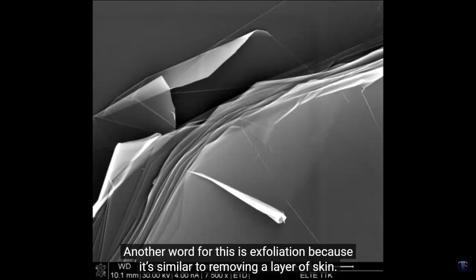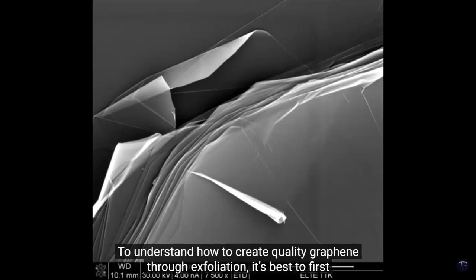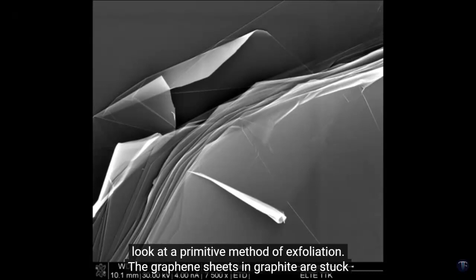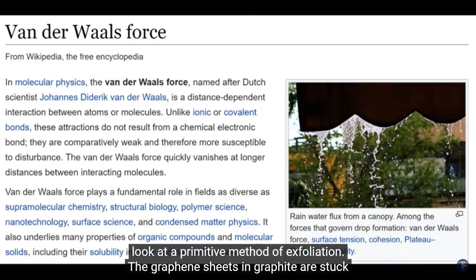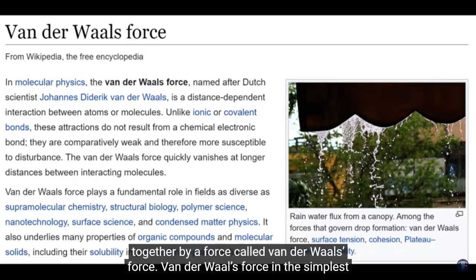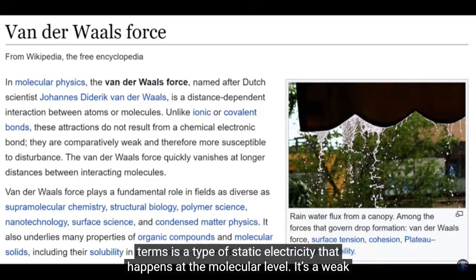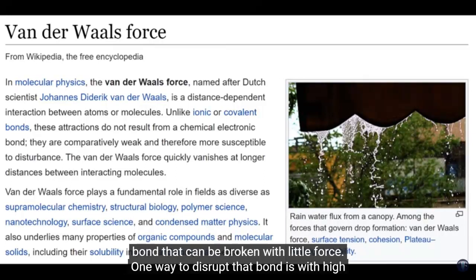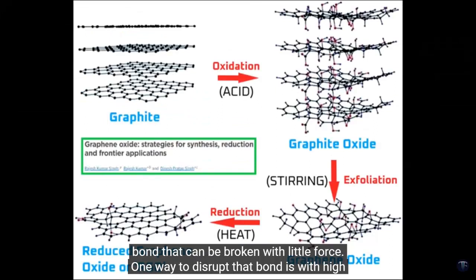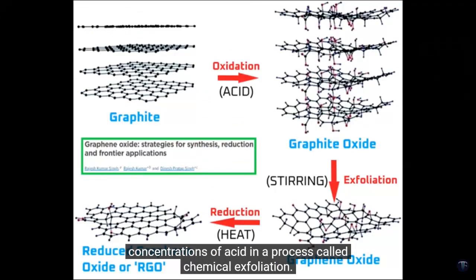To understand how to create quality graphene through exfoliation, it's best to first look at a primitive method of exfoliation. The graphene sheets in graphite are stuck together by a force called van der Waals force. Van der Waals force, in the simplest terms, is a type of static electricity that happens at the molecular level. It's a weak bond that can be broken with little force. One way to disrupt that bond is with high concentrations of acid in a process called chemical exfoliation. The acid disrupts the bonds by turning the graphite into graphite oxide.